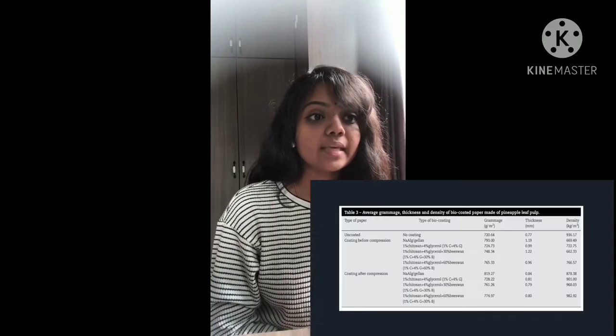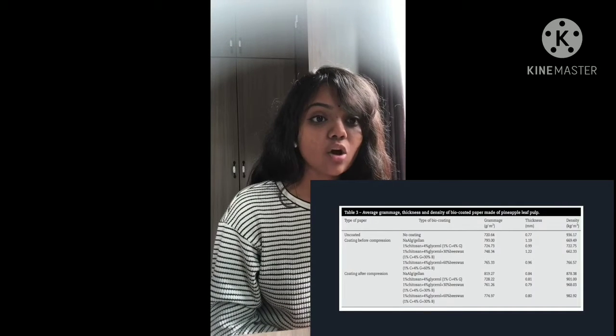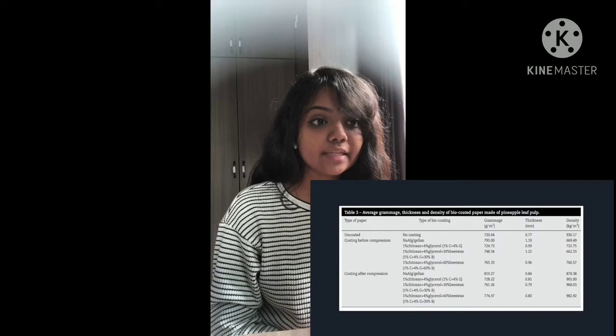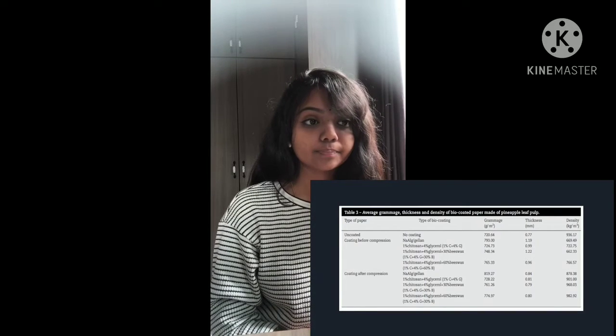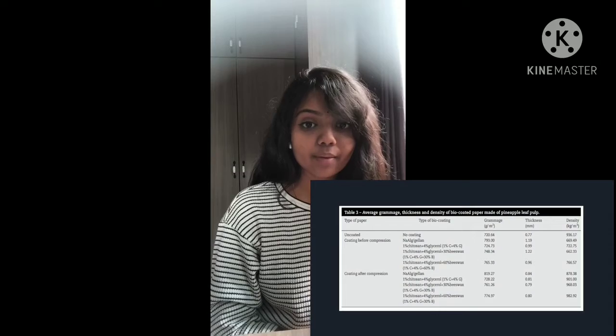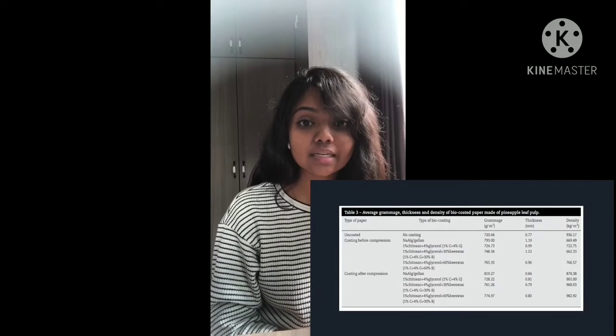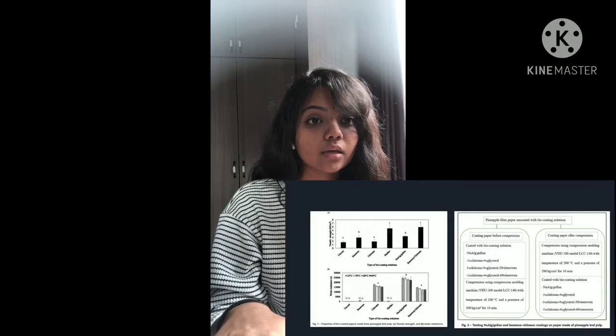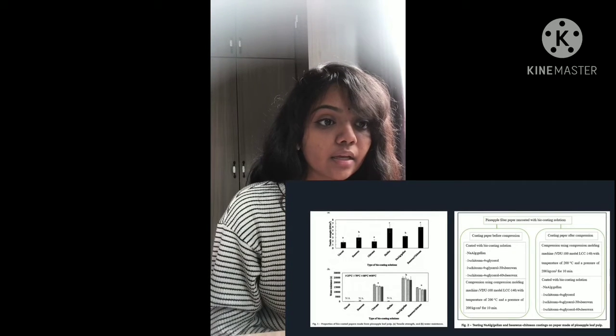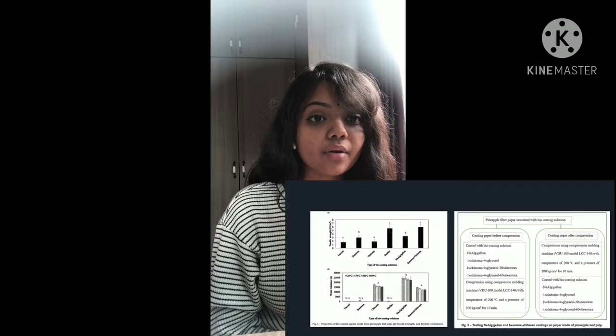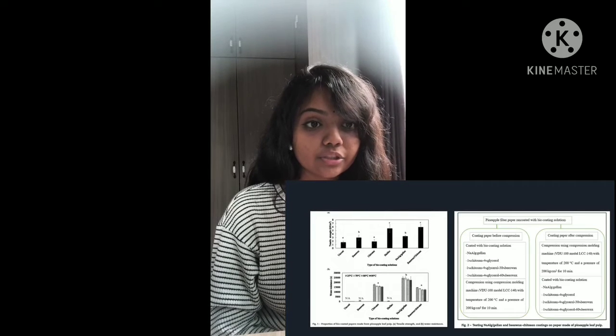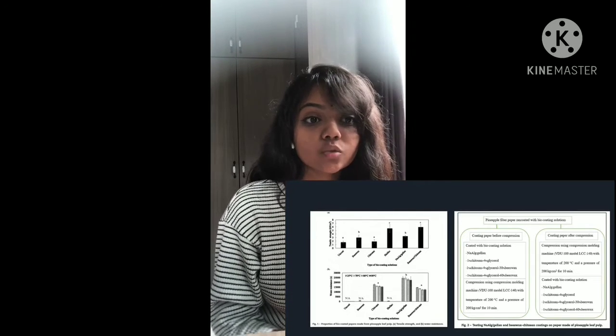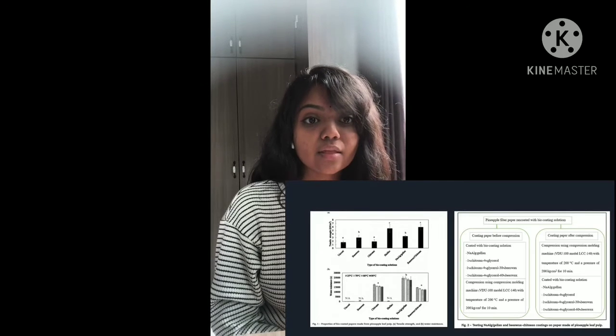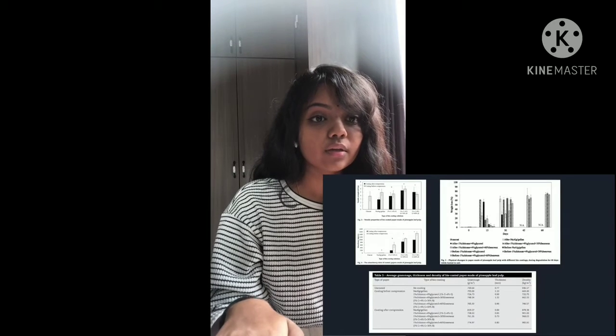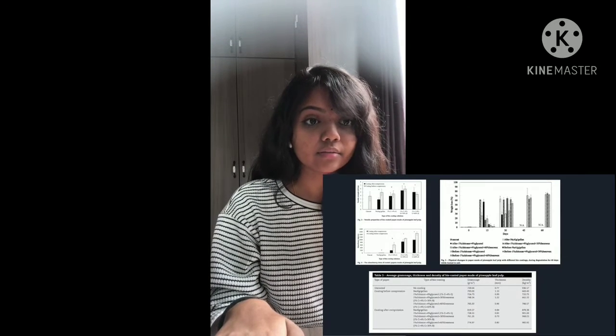And the next table is the average grammage, thickness, and density of biocoated paper made of the pineapple leaf pulp. What was recorded was the type of paper, the type of biocoating, the grammage, the thickness, and the density. So you can see in this table, they have written the pineapple fiber uncoated and with the biocoating solution, and this was the coated paper before compression and the coated paper after compression. And these are just all the results that were observed and recorded.